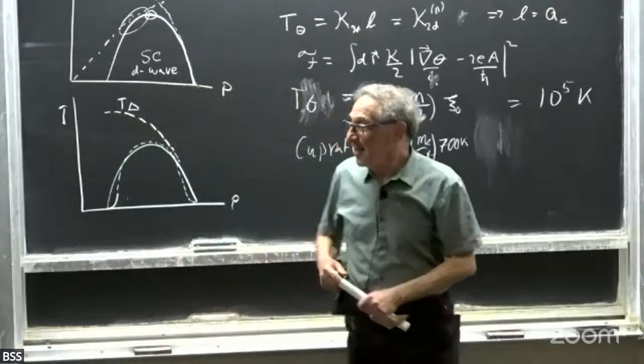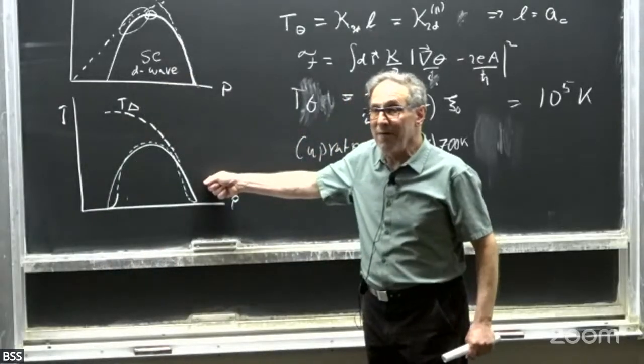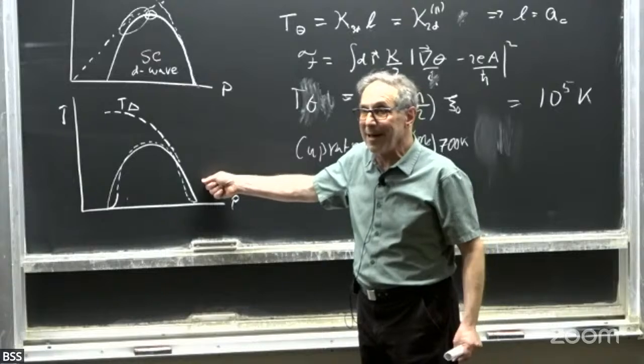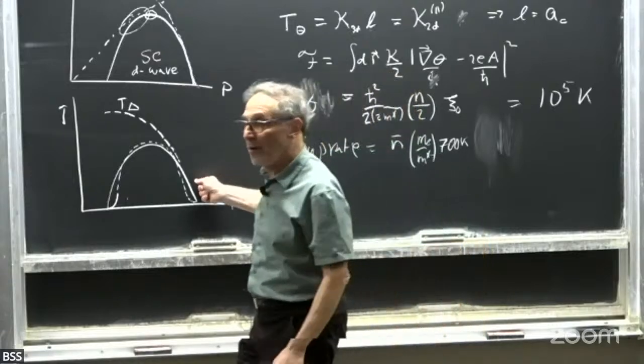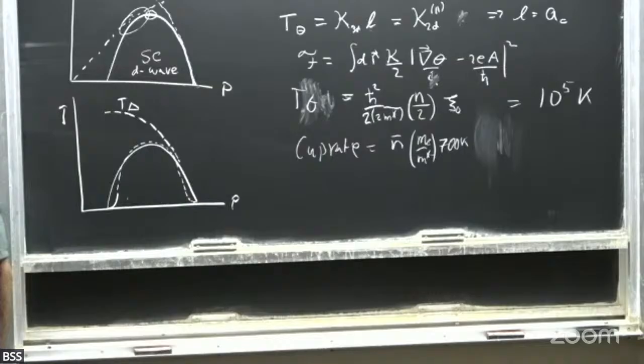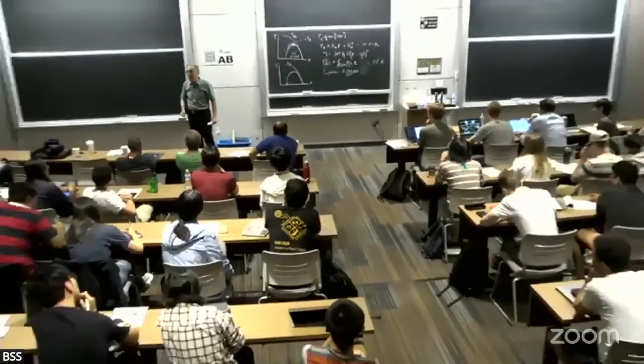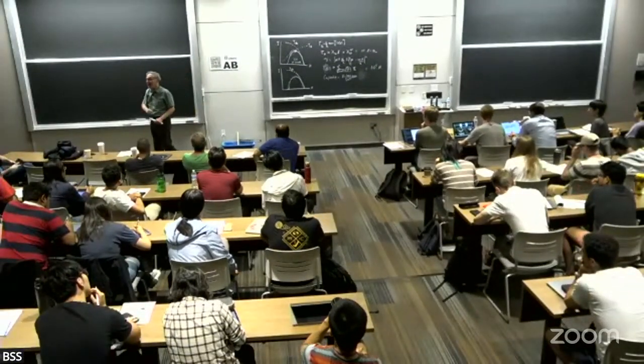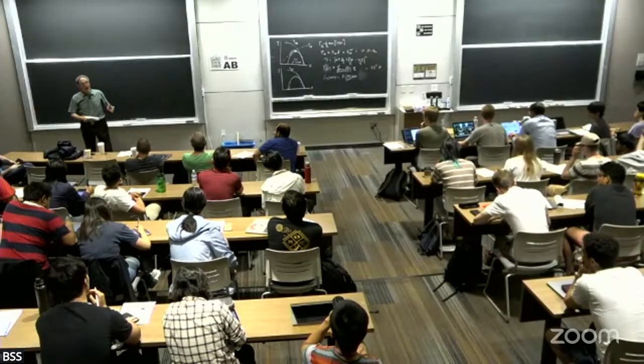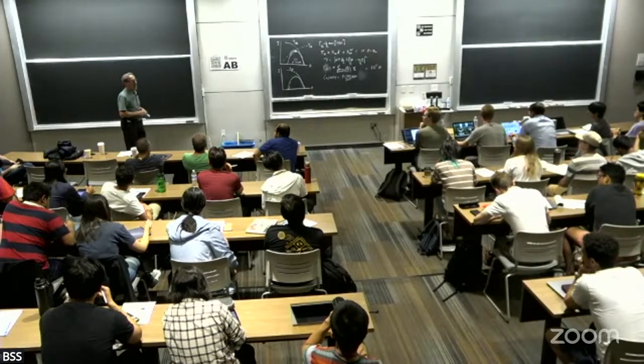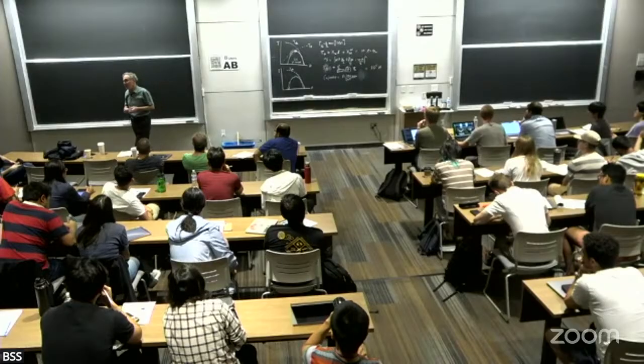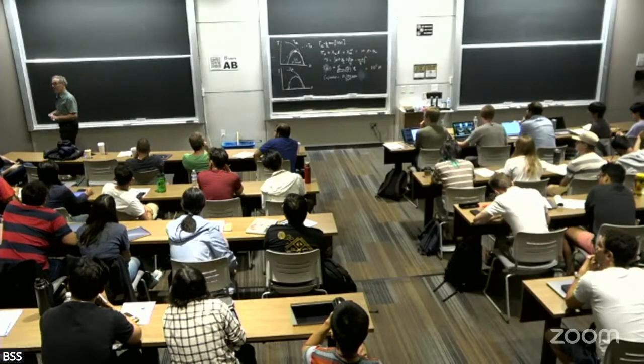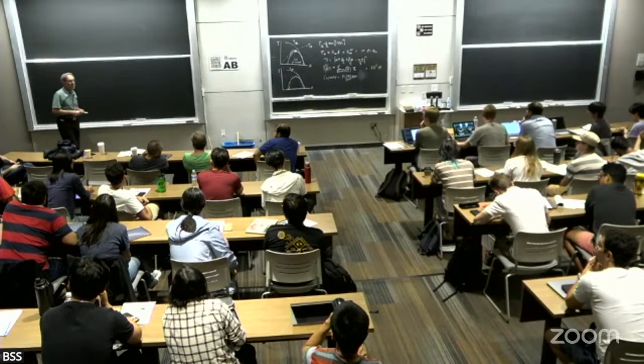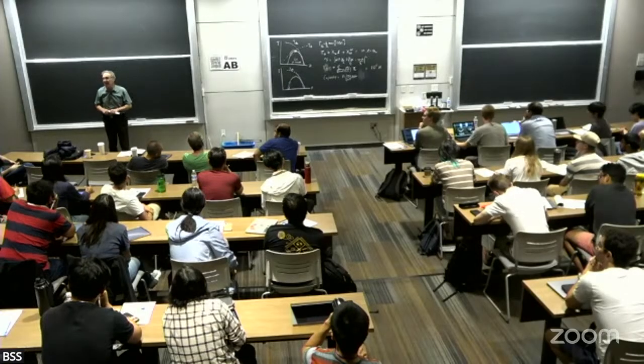Now, this was actually known when Vic and I wrote our paper in 1995. It was called the boomerang effect. That the superfluid stiffness rises through roughly optimal doping and then drops again as you overdope. So that was the boomerang effect. We commented on it, but we said, you know, in those days, the overdoped materials were not under very good control. We said this was probably due to bad samples.